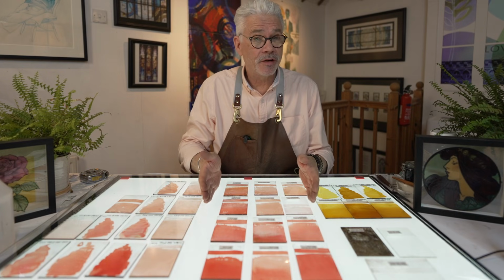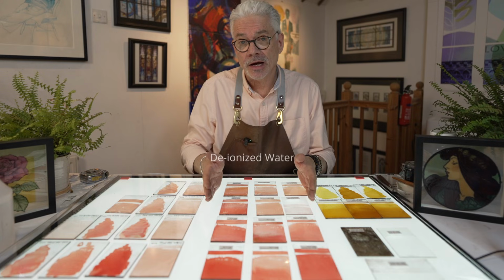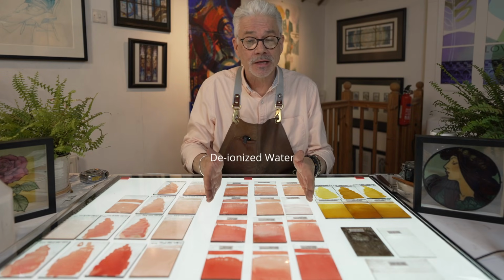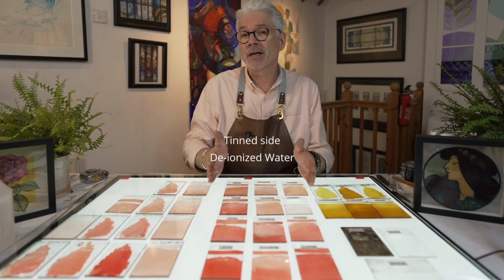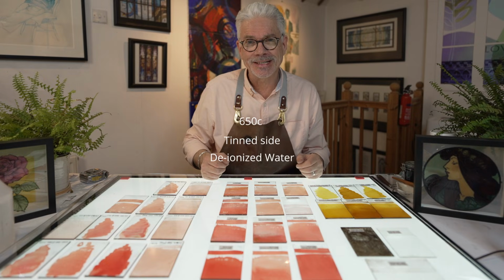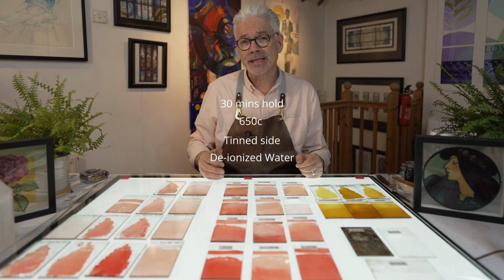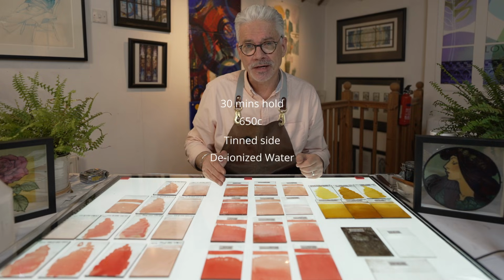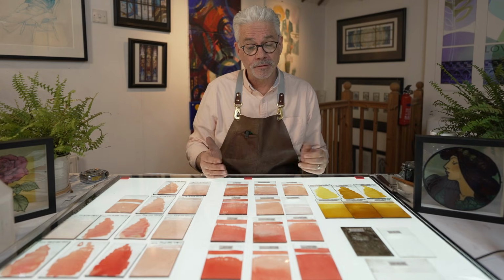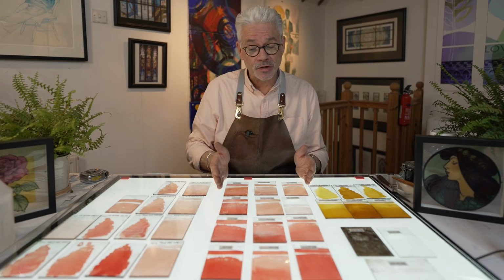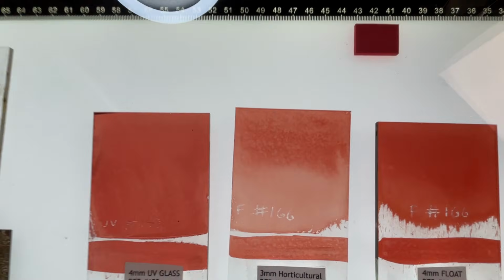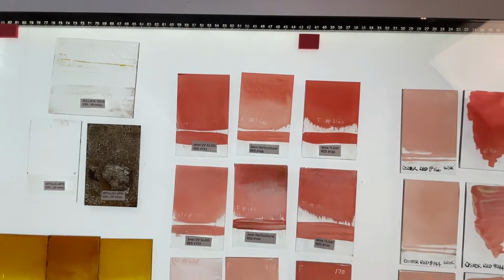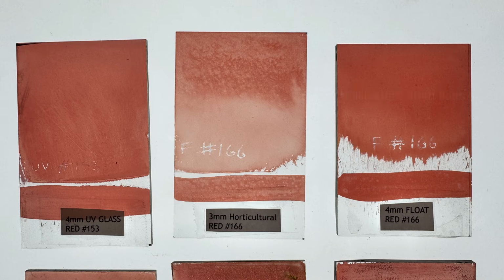So how did I achieve these results? I used deionized water. I fired the paints on the tin side. I fired them up to 650 degrees centigrade, and I held them at that temperature for 30 minutes, then switched the kiln off. That achieved these results. The 3mm glass doesn't react as strongly as the 4mm glass. The best glass is the Pilkington's 4mm float glass, and the best stain in my results is the red 166.